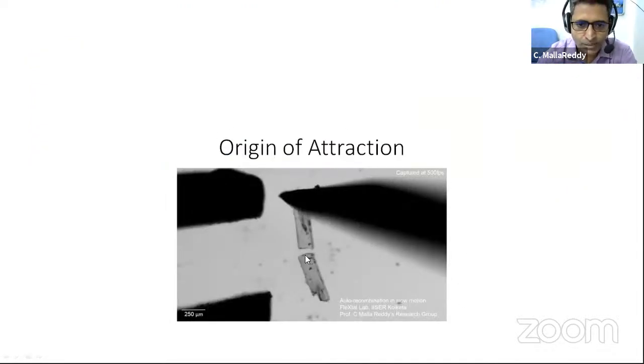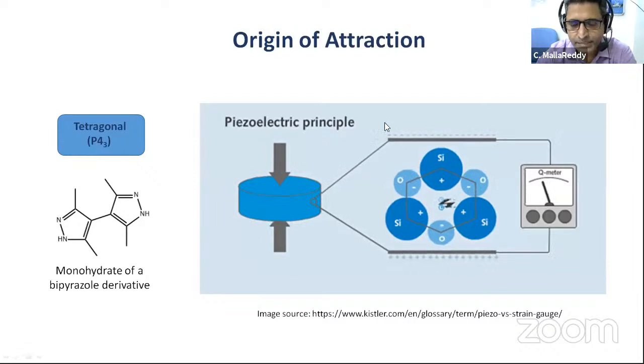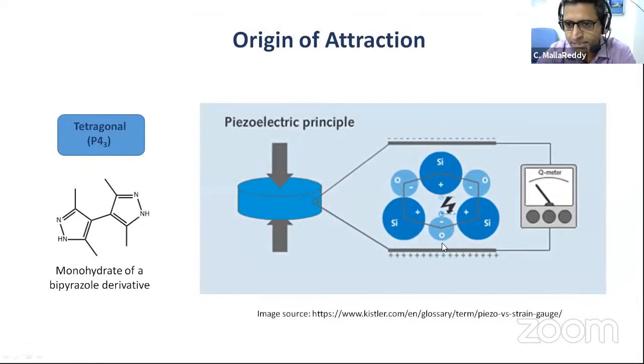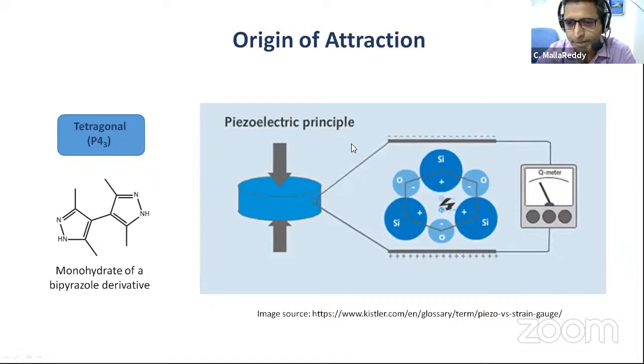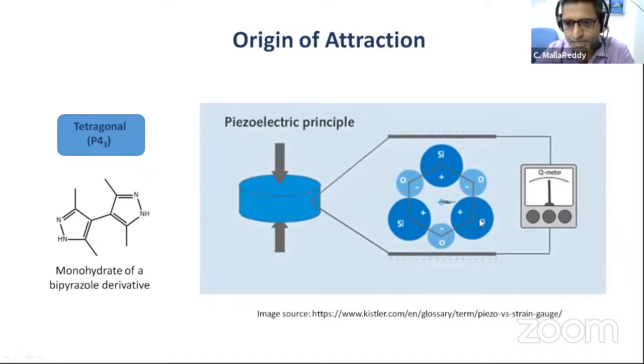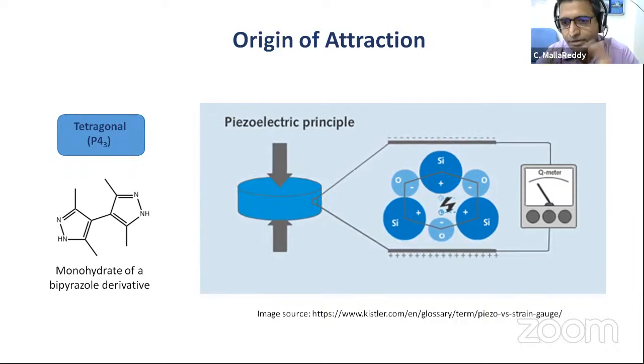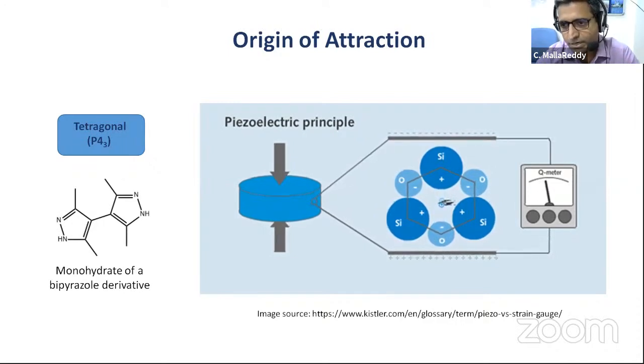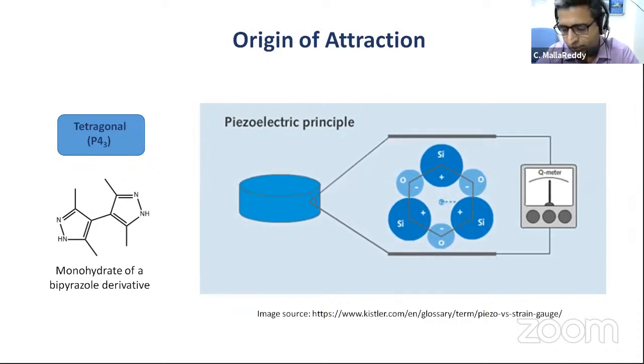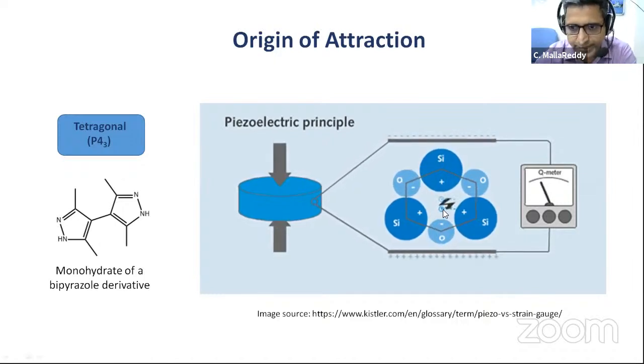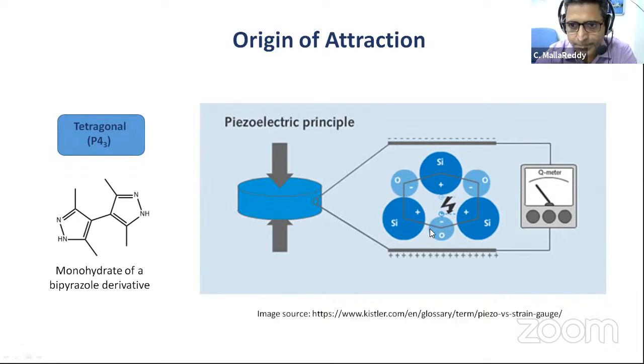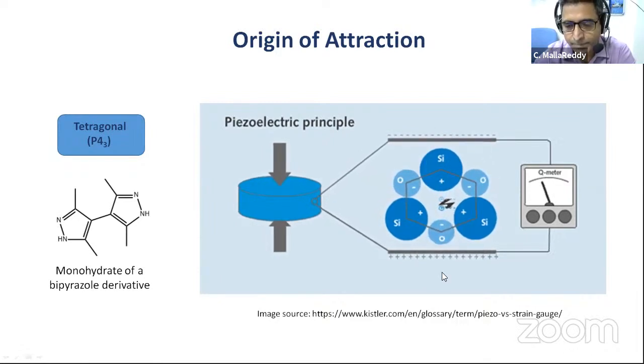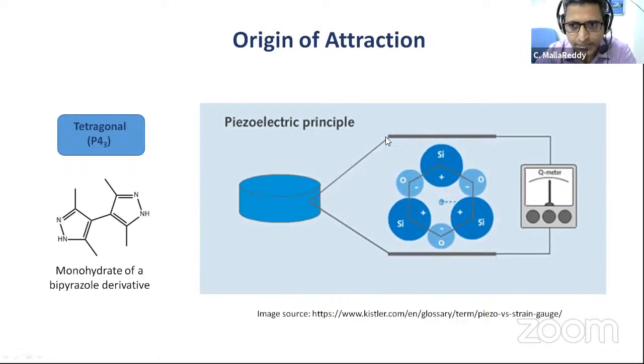Then we wanted to understand what is causing these pieces to come together. So what is the origin of the attraction? As I said, this is a piezoelectric space group. When you apply mechanical stress on piezoelectric materials, there will be an anisotropic distribution of the charges. So you disturb the charges, and then you generate potential. And then when you release, if this material is truly elastic, it would recover completely and you don't see the charges. It goes back to its original position. But if it is a slightly plastic deformation, if it's not 100% elastic, then you would have some partial charges, right? Some charges would still be there on the surfaces.